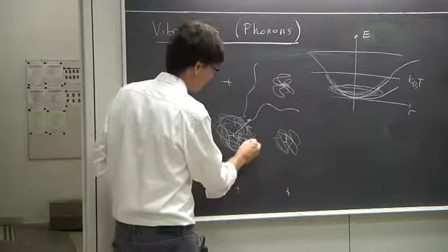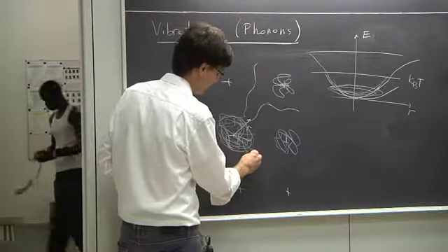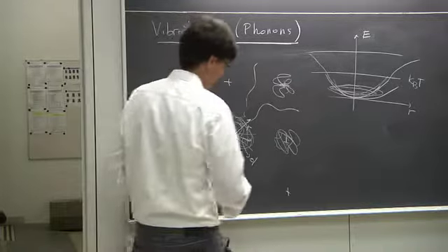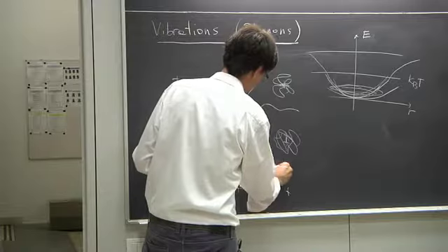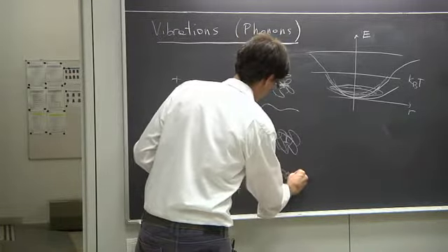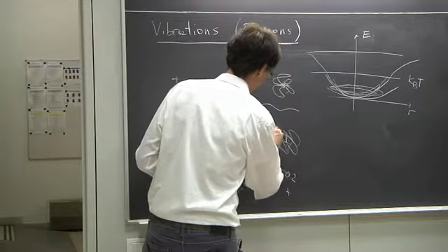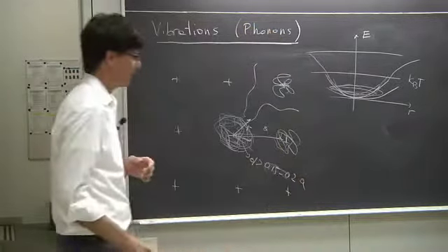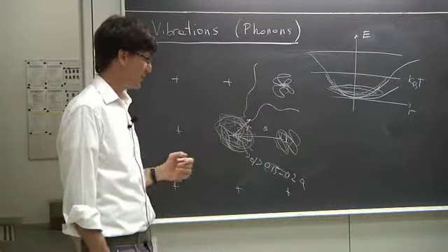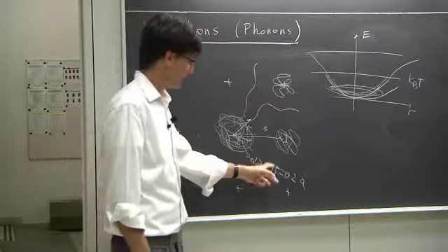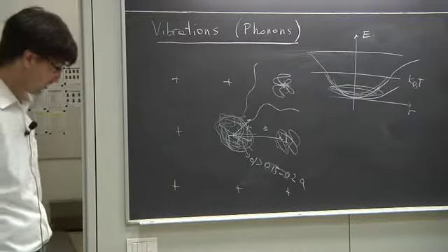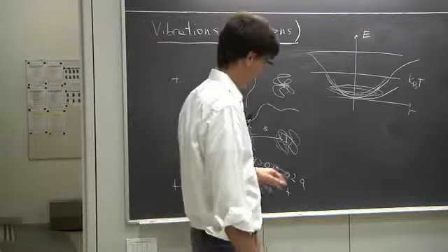So the rule states that as soon as the amplitude d of fluctuations of a particle around the nucleus exceeds something of the order of 15 to 20% of the interatomic distance a, as soon as the temperature is such that this condition is violated, that is, the distance becomes larger than 15-20% of the interatomic distance, 99% of the materials will melt.